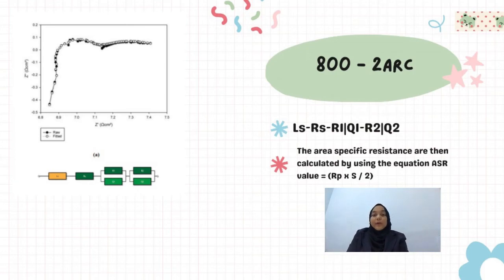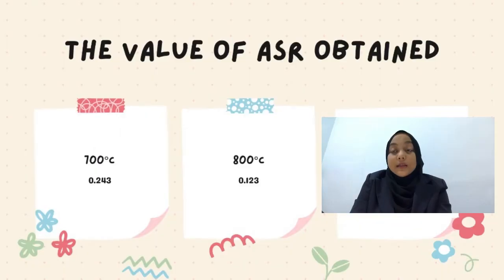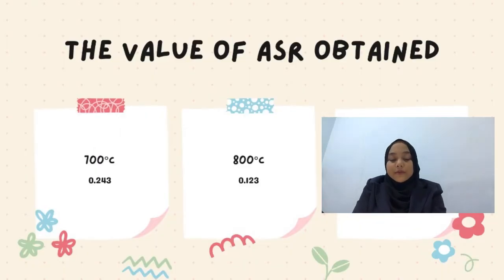As mentioned before, by using the equation mentioned, the value of area-specific resistance, ASR, is obtained. The value of ASR obtained for 700 degrees Celsius is 0.243 ohm centimeter squared, and the value of ASR for 800 degrees Celsius is 0.123 ohm centimeter squared. The value obtained can be considered as a good value, as it is in a lower range.